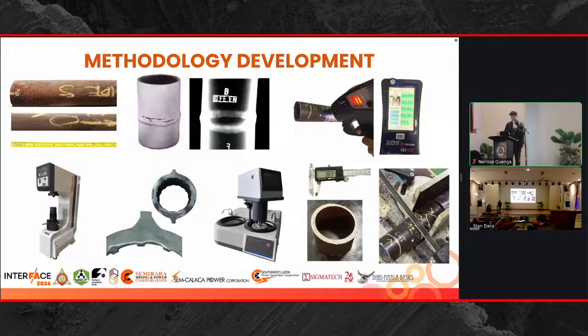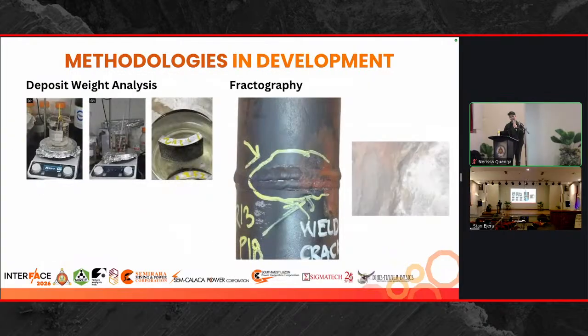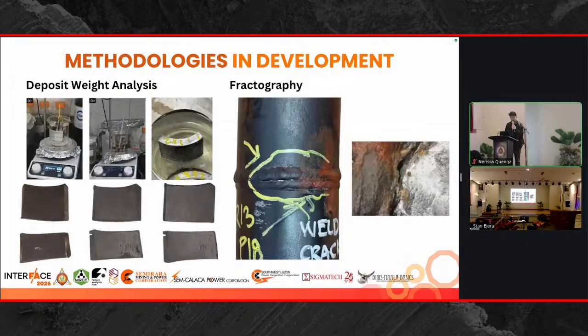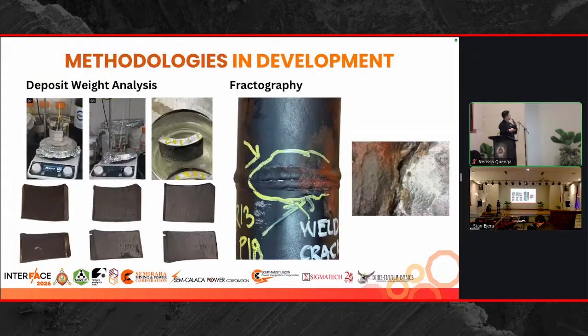So since we are broadening our testing capabilities, here are some of the methodologies that we are currently developing. So first is the deposit weight analysis. Basically, this test aims to quantify how clean the boiler tube sample is, because over time on a boiler tube's operation, scales or deposit accumulate on the inner surface of the boiler tube.